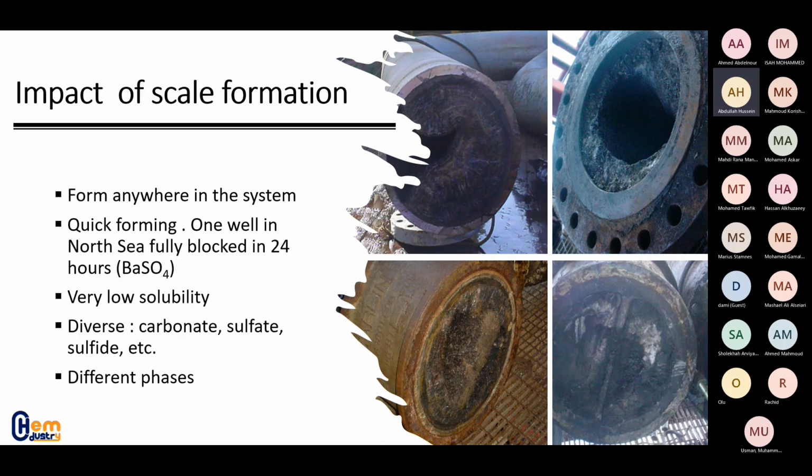Also, they have very low solubility. They can form in thick layers, very hard to remove. And it's not just one compound. They are diverse. There's sulfates, sulfides, halides. There's all kinds of different compounds. And there's also different polymorphs and phases for the same compound. Which complicates the problem and makes it very elusive and needs good